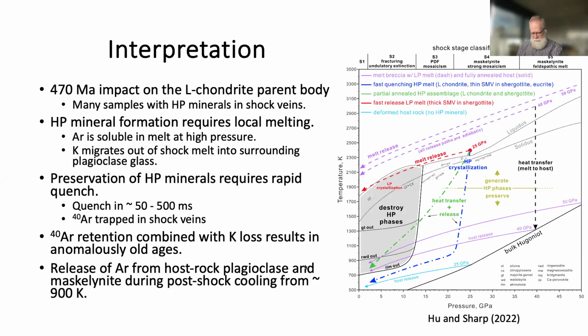so in the interest of time, I'm not going to go through all this, but basically we have that 470 Ma impact. The high pressure minerals require local melting. Argon is soluble in silicate melts at high pressure. There are some experimental studies that demonstrate this, but what's not clear is that potassium must not be soluble in this melt. It must come out as a separate phase, a vapor phase or a liquid phase that's not compatible with the silicate melt at high pressure, and that escapes the melt vein during shock.